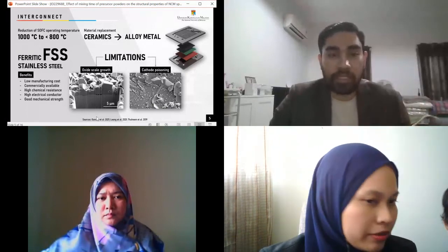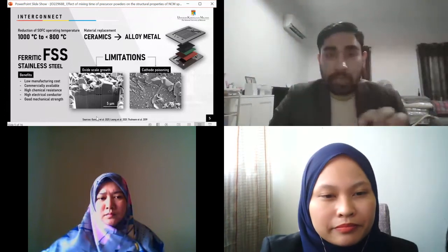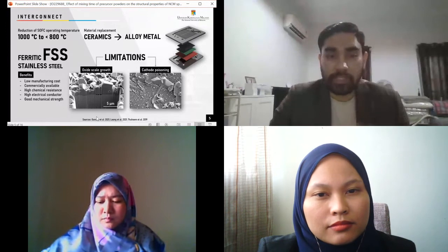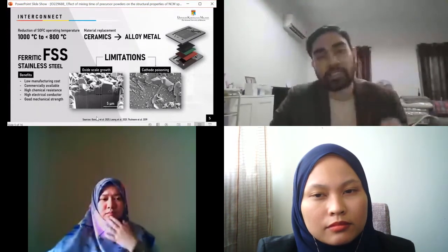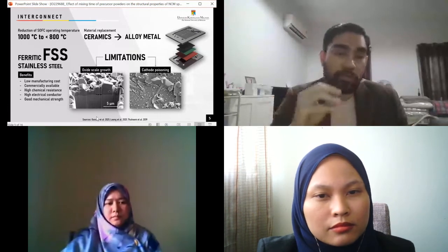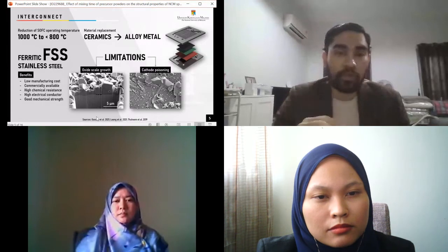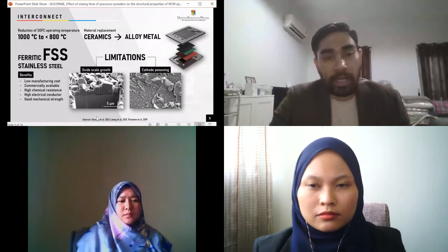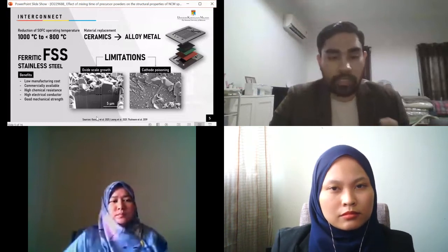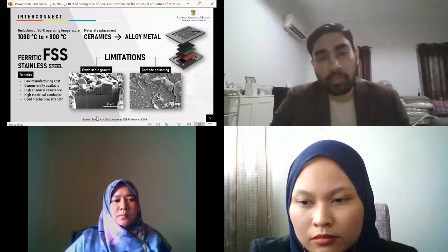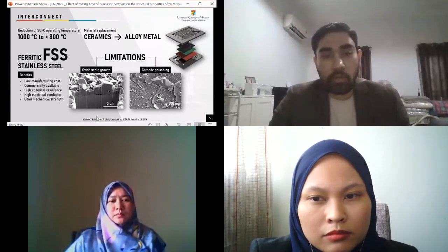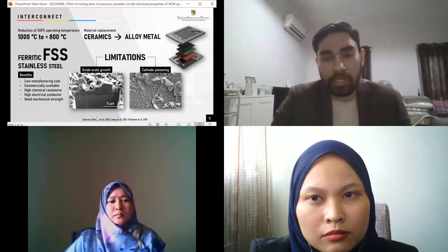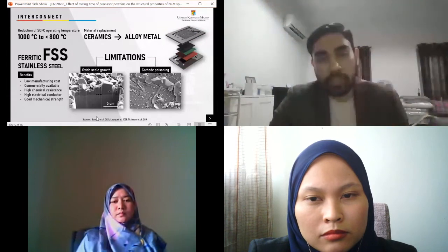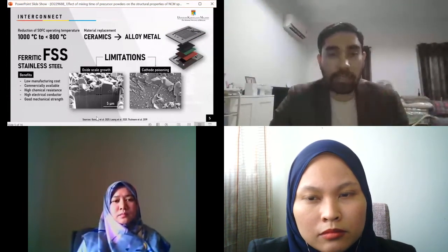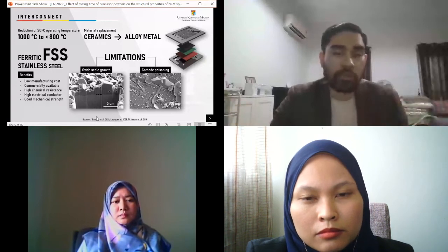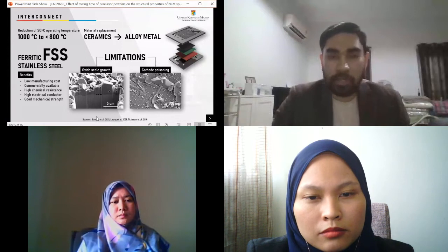However, when this material is exposed to the solid oxide fuel cell operating environment, it has several limitations. So the first one is the growth of oxide scales. This oxide scale is highly rich in chromium, which is highly volatile when exposed to an environment that has high oxygen partial pressure. So this chromium volatilization can cause poisoning, which is the second problem of the material, towards the neighboring components, especially the cathode, because in the cathode environment, the oxidant is flowing through the component, which has high oxygen partial pressure compared to the anode side. That's why on the cathode component, this problem is more severe compared to the anode side.